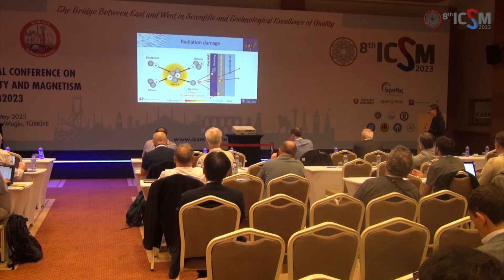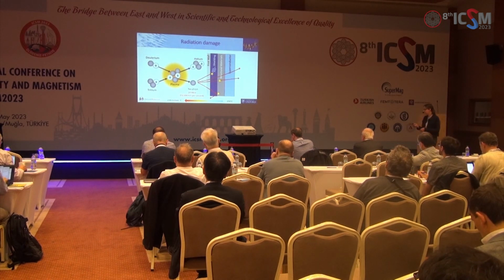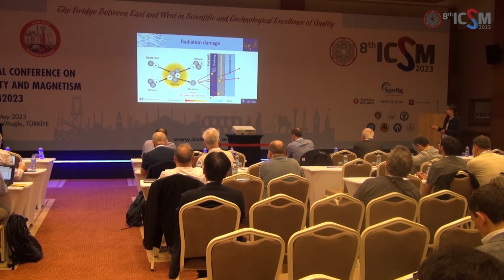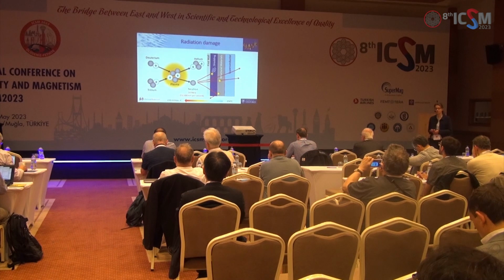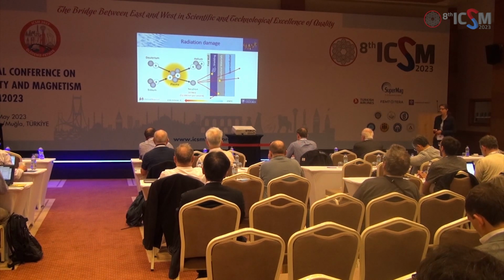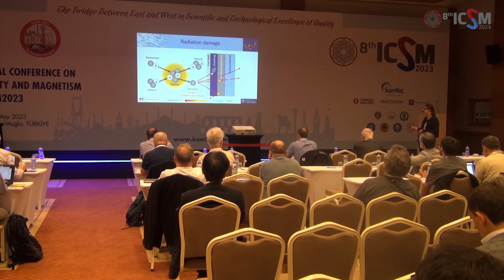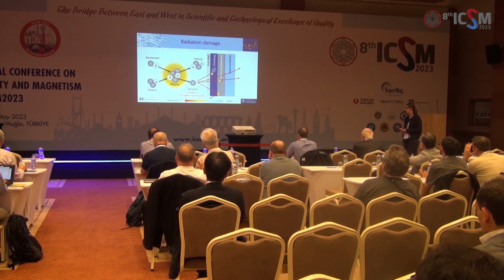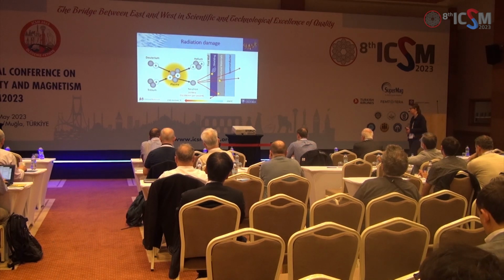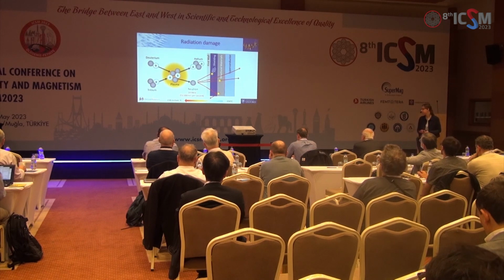So in the fusion reactor, we have deuterium and tritium reacting together in the plasma to form helium nuclei and a neutron. And these neutrons are very high energy, about 14 megaelectron volts. Because neutrons are neutral, they don't interact very strongly with materials, which means that they pass through. They can pass through the first wall, some of the shielding, structural materials, and they'll get to the superconducting windings, particularly in a compact reactor where there's not very much space for all these components in front of the magnet.